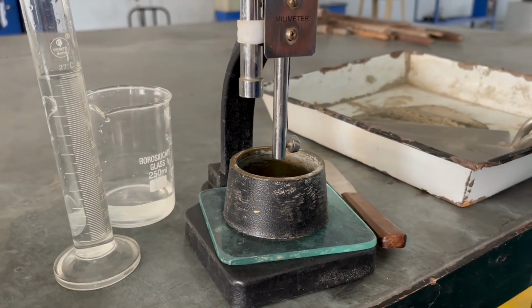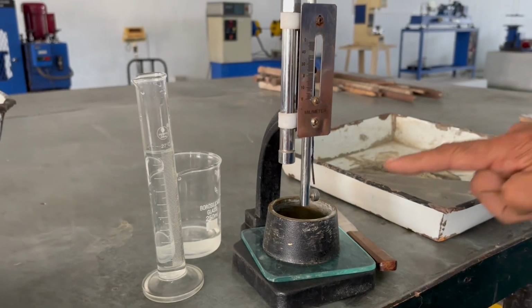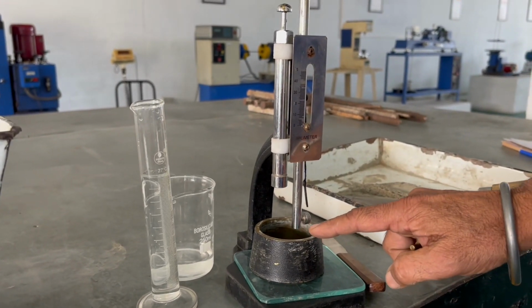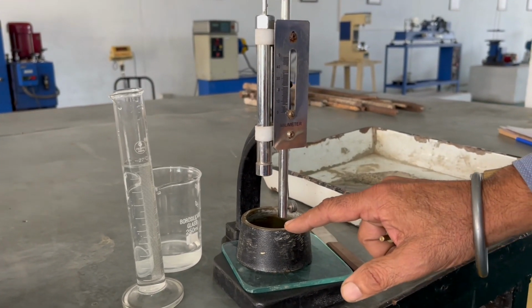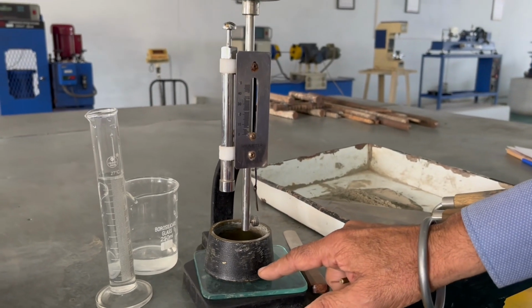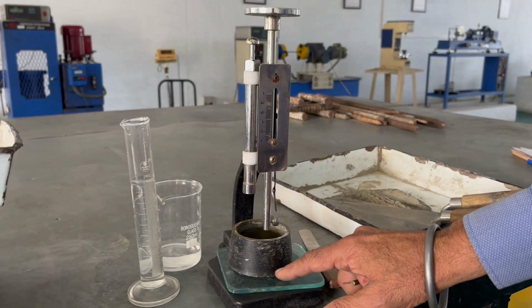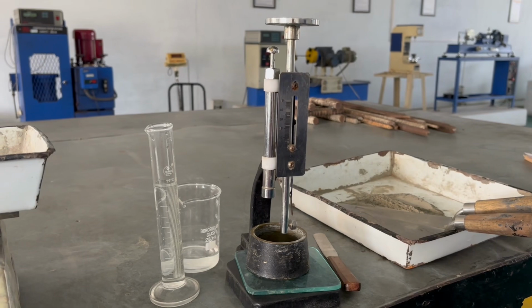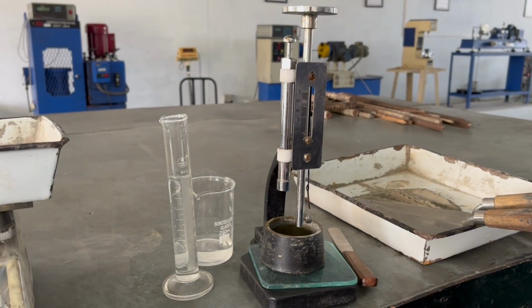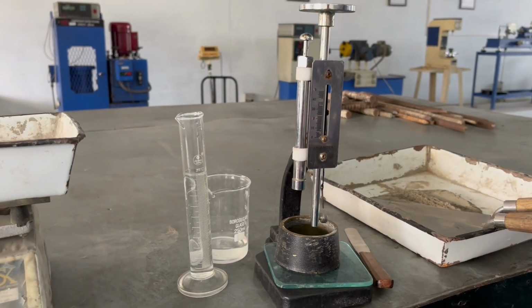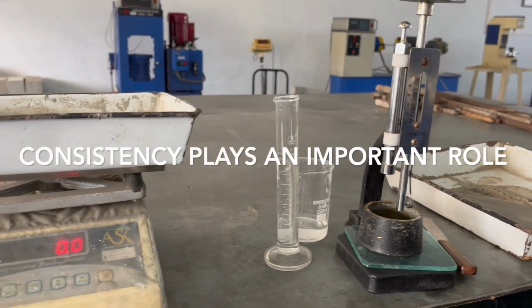In other words, it will be 33 to 35 millimeter from the top of this mold, or 5 to 7 millimeter from the bottom of this mold. So this is very important because the consistency plays a very important role.